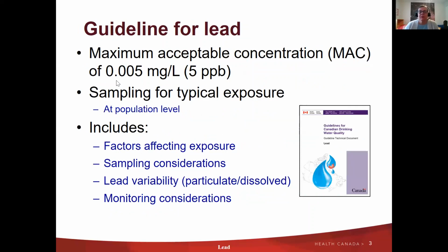As I said, for our guideline for lead, we established a maximum acceptable concentration of 5 micrograms per liter, or 0.005 milligrams per liter. Some people call it ppb. So that was established back in 2019. And in that document, we identified sampling for typical exposure at a population level. It also includes factors affecting exposure, some sampling considerations, as well as lead variability, which can lead to distinct types of lead, which are either particulate or dissolved in nature, as well as some of the monitoring considerations.